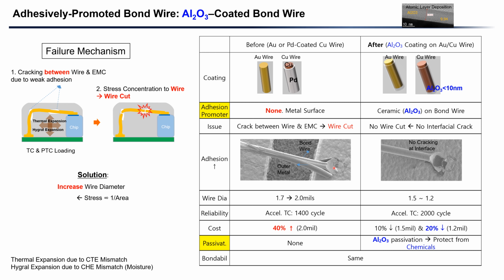For instance, on the conventional bond wire without adhesion promoter, when we apply the deposition of an outer metal additional layer so that we can induce the interfacial cracking, and when we apply the stitch bonding, which is nothing but external mechanical loading, terribly weak adhesion we have seen. However, when we introduced aluminum oxide coating as an adhesion promoter, we apply the stitch bonding, we don't get to see any interfacial cracking. From a different perspective, for cost reduction purposes, because now we have a better adhesion, then we can decrease the wire diameter for the cost reduction purposes.